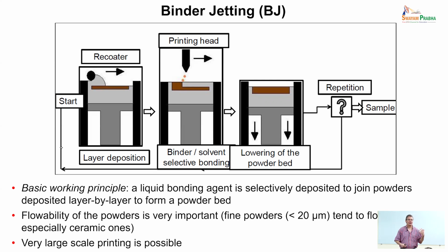And of course, if you do that with a ceramic powder, and I'm talking about fine particles because, you know, if you need to sinter, you need high sinter activity. And for ceramics, you typically use submicron particles for conventional processing. So if you use that type of powder, which is the one that you would normally use for making your ceramic part, then it is very, very difficult to obtain a defectless layer, because those powders are non-flowable.